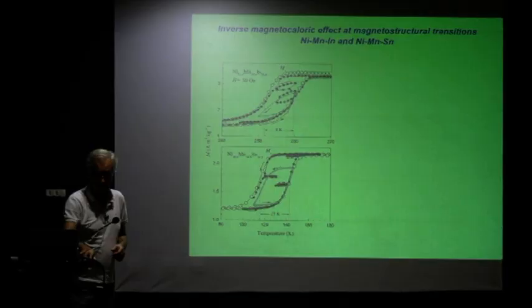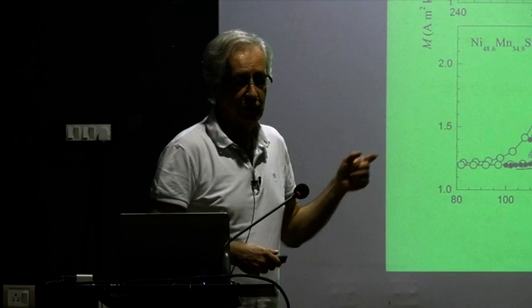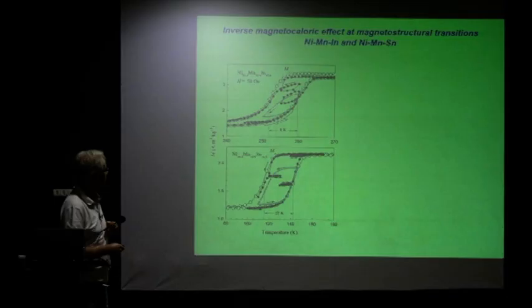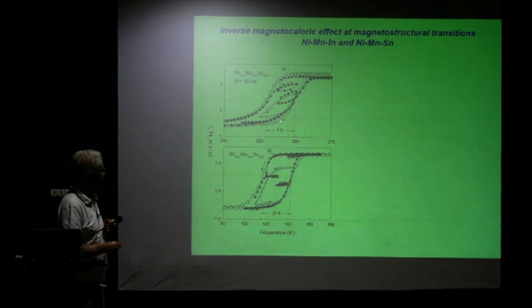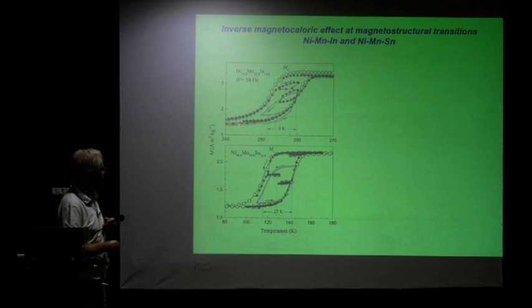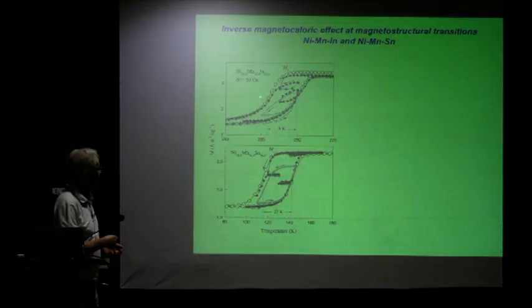Large hysteresis means about 27 Kelvin, and in the other case about 8 Kelvin. We tried going through the hysteresis under certain conditions. In the narrow hysteresis case, if we move around in temperature — measuring completely from the lowest temperatures up to high temperatures and back — we have the fullest cycles of course. Now when we go inside the loop, what happened?